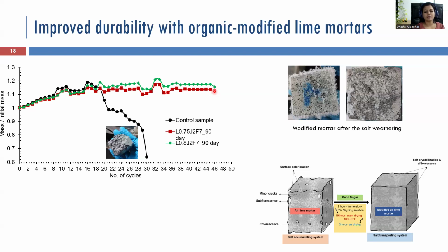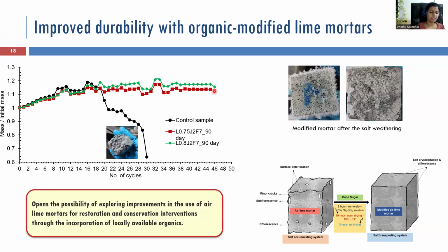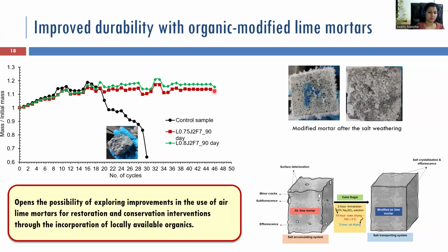But when you have modifications in the system with organic addition, especially fermented jaggery, and larger uniform pores generated in the system, it would prevent salt accumulation, and instead salt transporting could happen, enabling formation of efflorescence on the outside and preventing subflorescence formation. This opens the possibility of exploring improvements in the use of lime mortars for conservation practices by incorporating locally available organic additives.